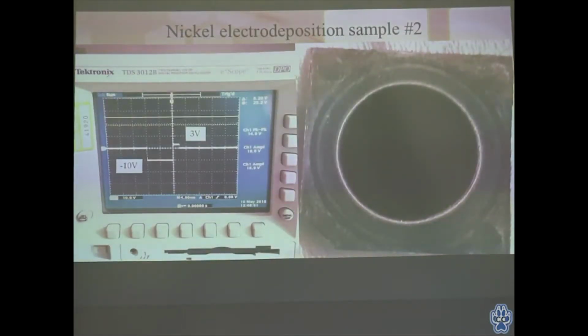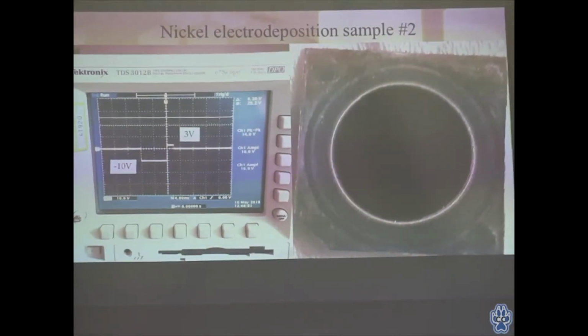So we decided to revise the pulse signal that we sent to our sample because obviously we had deposited too much nickel and covered the entire surface. We decided to keep going with a negative 10 volt to 3 volt kind of pulse signal, but on the previous signal, I forgot to mention, we used 2 DC power supplies in series to generate that pulse. Those DC power supplies weren't able to switch the voltages or really do it at a short enough pulse.